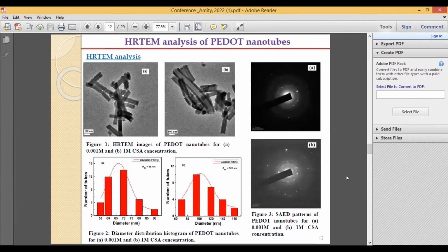Okay, so these are the HRTEM micrographs of our synthesized nanotubes. From the 10 micrographs we have taken, I have actually synthesized 4 different samples from 1 millimolar to 1 molar. We have taken micrographs of only 2 concentrations, that is the lowest and highest. It is seen that the micrographs confirmed the formation of very well ordered nanostructures, and we have